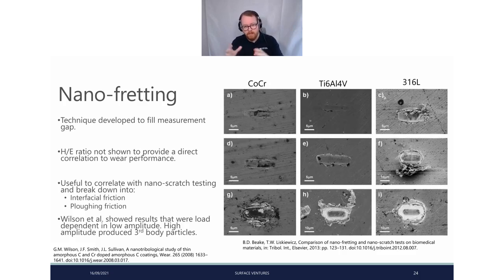And another thing I want to talk about, we typically associate this with the sort of micron scale, but of course, this sort of idea of a vibratory or oscillatory contact, we can scale this down as well to nanofretting, essentially filling in the measurement gap between AFM at the very low scale to our sort of micro fretting and sliding there. So we can think of this as sitting right in the middle. Typically with this, we look at H over E ratio, so hardness to elastic modulus ratio, that would normally drive and control a lot of the wear response for these small scale wear scenarios. However, that isn't quite the case here.